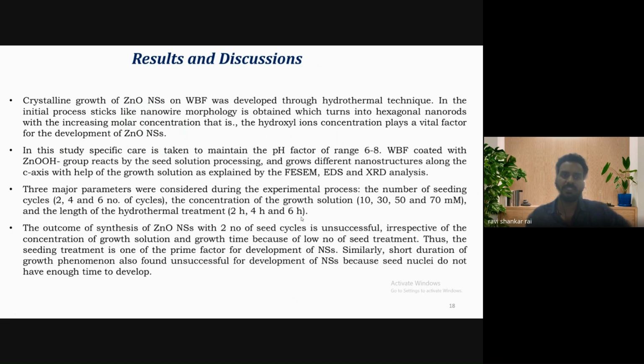In the initial process, stick-like nanowire morphology formed, which was further transformed into the ZnO nanostructure due to the increase in the molar concentration. Overall, the hydroxyl ion concentration plays a vital role in the development of ZnO nanostructure. We maintained the pH between 6 and 8, and it was found that the entire nanostructure has grown properly along the C-axis, and the growth was explained with the help of FESEM, EDS, and XRD spectroscopy.